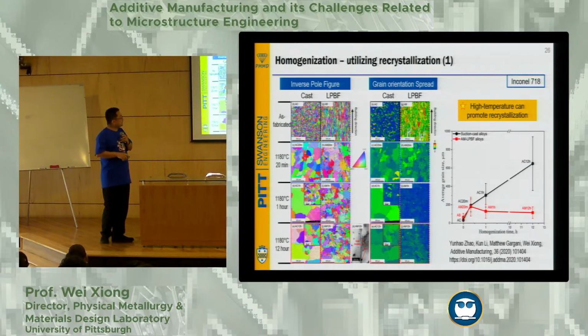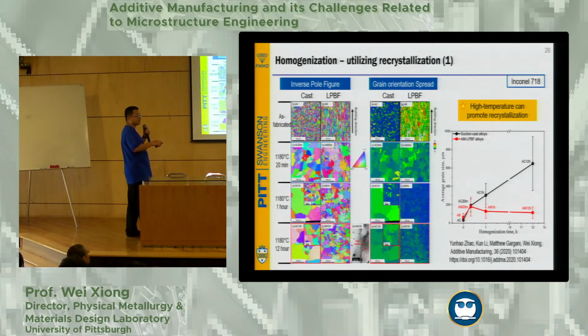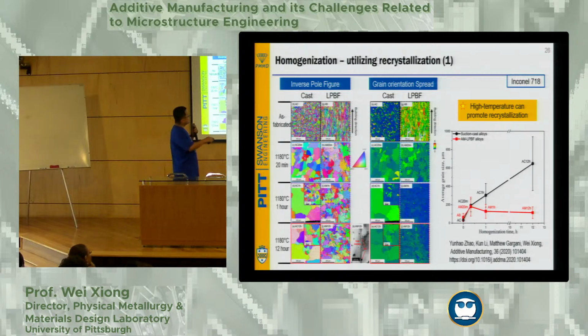We actually find the cast alloy does not have high residual stress as you compare with the printing process. So with 3D printing, you can introduce a lot of residual stress in the beginning. So if the color is red and green or yellow, that's actually a high residual stress indication at the grain level, okay? Not forming a crack.